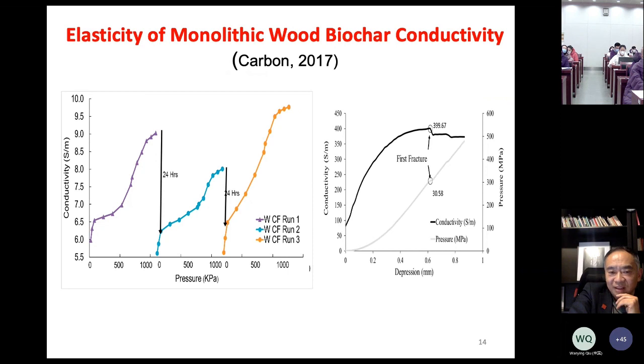elasticity of conductivity. What that's supposed to mean is that if you apply pressure to the monolithic biochar, the conductivity will increase. So what you can see here is that with an increase of pressure, conductivity actually increases. But if you release the pressure, the conductivity decreases. He did that experiment, say, after 1 day, and he repeated it, and those properties were retained.